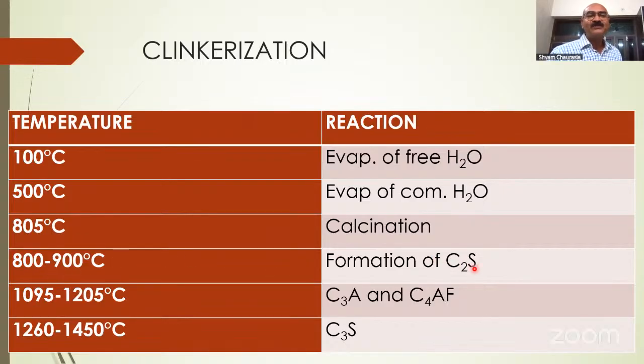So the formation of C2S, dicalcium silicate: 2 parts of CaO combine with 1 part of silica, so they form C2S, 2CaO·SiO2. This is the first combination reaction, between these 2 oxides. Then the next formation is between 1100 to 1200 degrees centigrade.